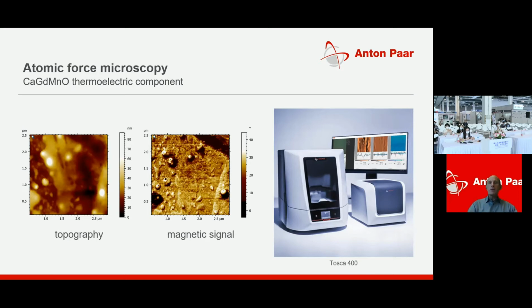The same area of 2.5 by 2.5 square micrometers was scanned by the cantilever tip with the hard magnetic cobalt coating. The phase plot obtained from the magnetic force microscopy shows areas of different magnetic response, which coincide with the topographic structure of this material surface.